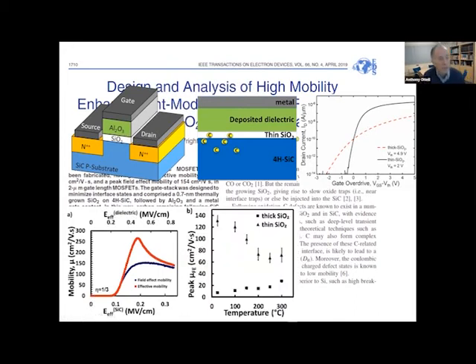And when we look at this, we can confirm where that's coming from. This is a plot of mobility as a function of temperature, which when the PhD student who measured this saw it, he came back and was really distraught because he couldn't understand. We were expecting the mobility to be higher, and the thin oxide data clearly is higher, but as temperature increases, it goes down. Whereas with the conventional poorer mobility, it increases with temperature. And the reason for that is that they're indicative signatures of what's causing the scattering and therefore reducing the mobility.